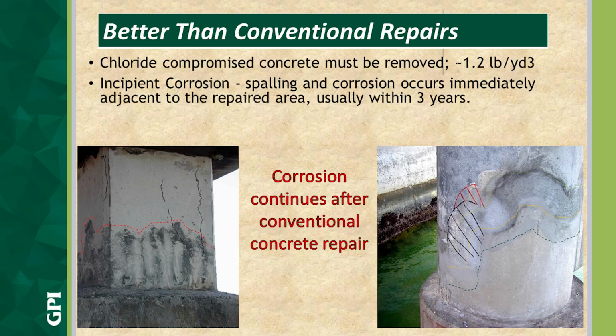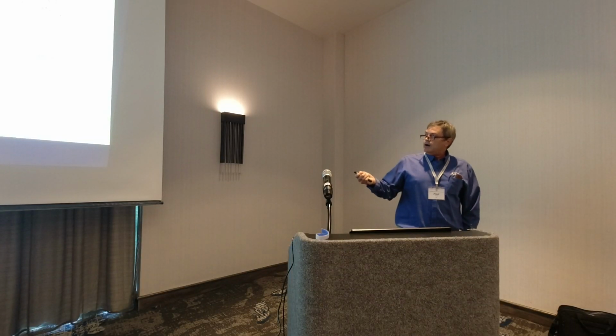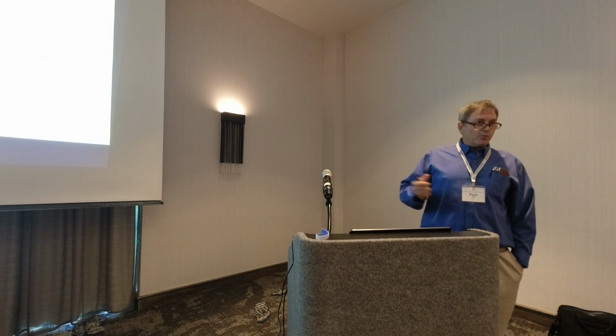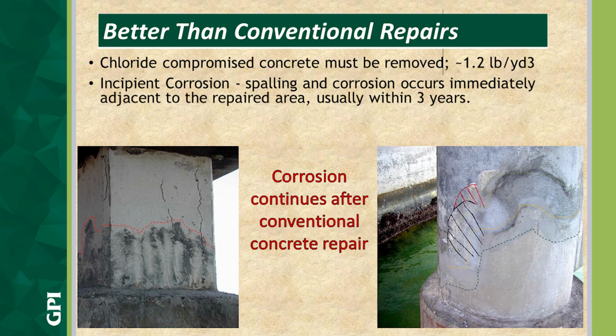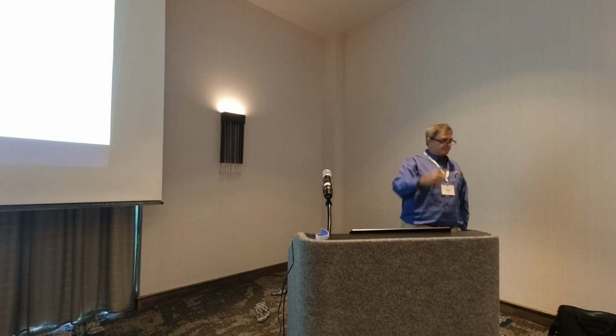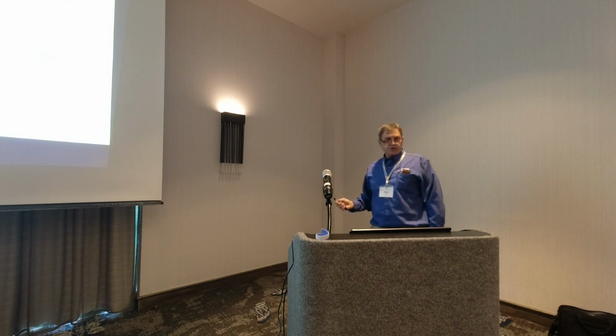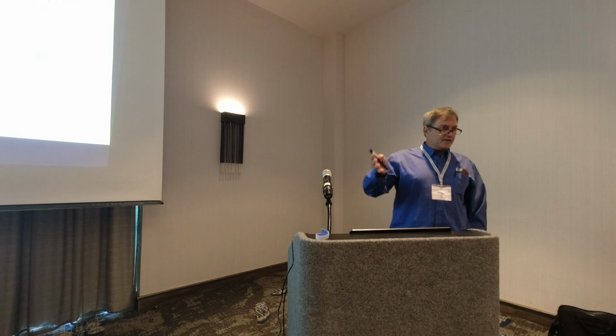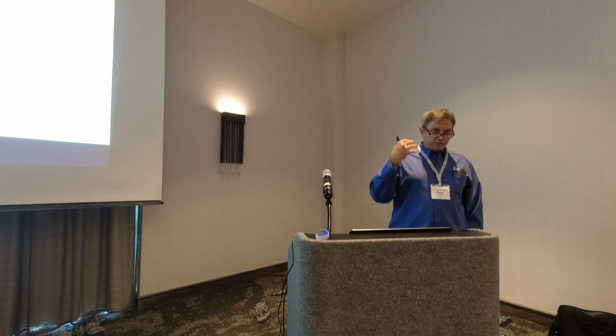So why is CP better than traditional repairs? Well, chloride compromised concrete must be removed. If you're spalling and having issues, you're already in trouble. Normally the rule of thumb is about 1.2 pounds per cubic yard of chlorides. That can change with your mix design, your alloys, things like that, but it's still a pretty good rule of thumb. If you test your concrete and you have higher than 1.2 pounds per cubic yard, you're past what we call the initiation phase, and corrosion will begin.